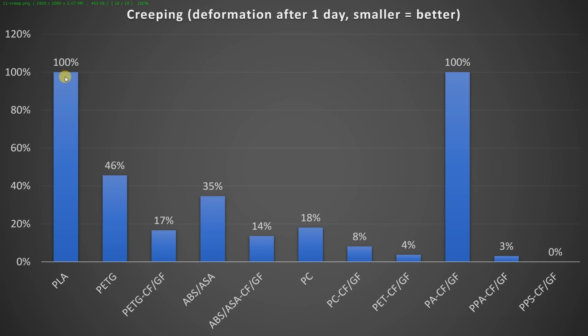If the temperature were just a little bit bigger, let's say 35 degrees Celsius, this difference would be even bigger. From the basic materials, the second best is PETG, and then ABS-ASA. That's why this material is recommended for the Voron parts, for example. Another conclusion, that the fibers always help here a lot.